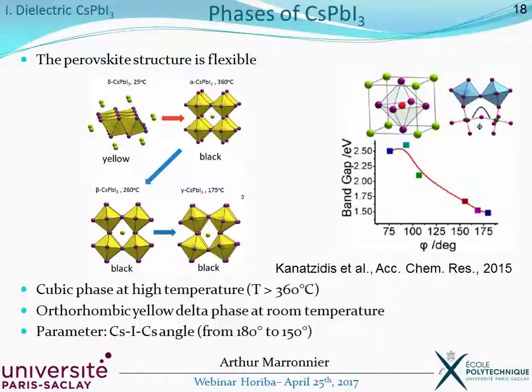The perovskite structure is flexible, meaning that it will have different phases depending on the temperature. As you can see, the structure can bend, and you have a tilt angle here, phi, which will change the band gap, by the way. And you have mostly a cubic phase at high temperature, here the black alpha phase, and different orthorhombic phases at room temperature. Here we study both the cubic phase and the orthorhombic phases, mainly the delta phase.